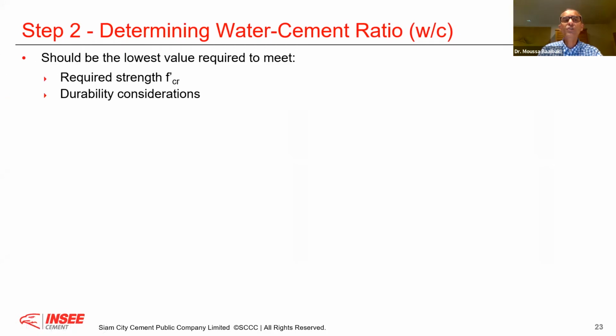Now, when we come to the determination of the water cement ratio, here you should take the lowest value that is required to meet either the required strengths. For example, I design my slab, I need 25 megapascal. But if my slab is an exterior slab, I have to take durability consideration, and suddenly it is not 25 megapascal, but 38 megapascal. Therefore, I need to consider the water cement ratio that is the lowest to achieve the required strength or the durability consideration.